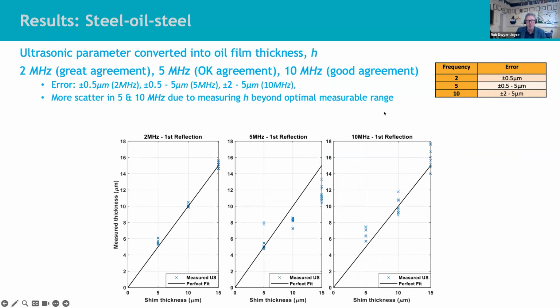So if you convert that to film thickness using that equation that I showed you on the third or fourth slide, you get very good agreement for these low frequency transducers. So that's easy, that's quite successful. If we use the right kind of frequency, 2 megahertz, we've got a good stable signal, and we can get good measurements of oil film thickness.